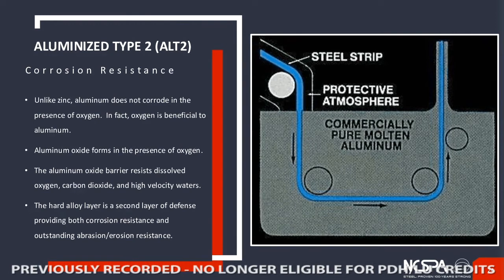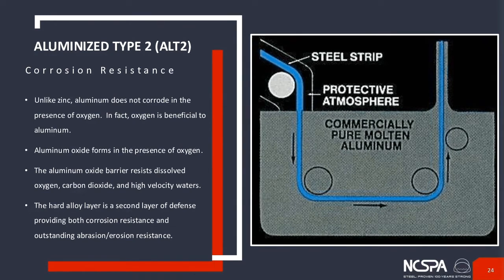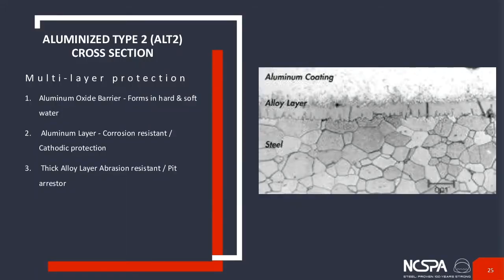Interestingly, and I'll show you here in a second, a cross-section micrographic photo on the next slide, it's again unique because the steel and aluminum form a very hard aluminum steel alloy in between, and that looks like this on the right. If we went back and looked at the same microscopic photograph of the galvanizing and zinc, this layer is quite thin, and aluminum and steel in the right conditions form this big, thick layer in the middle. So it adds protection to the system in addition to just the pure aluminum coating. So, like I said, quite a bit different animal from galvanizing.